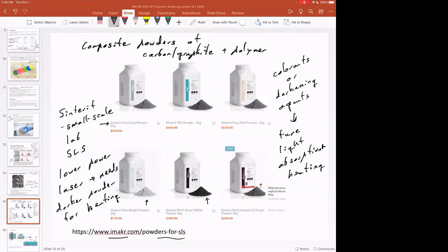They just have a darkening agent in there, and the darkening agent doesn't necessarily change the mechanical properties of the material per se, but it changes the absorption of the laser, especially in different machines where you don't necessarily have high power lasers that you can get good sintering of white powders in. So that's just a heads up on if you're going out and buying SLS powders, what to look for, or another tweak if you're designing SLS powders, you can modify the light absorption by making a composite powder. So that's something to remember.